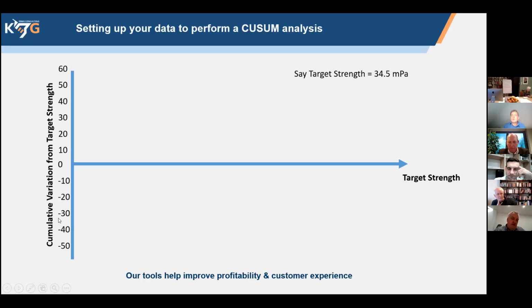On the y-axis here, we have cumulative variation from target strength, and I'll just have a very, very quick little animation to show you how the system works. So the first test result that you have, remembering the target is 34.5 MPa. The first one in the series is 37 megapascals. The plot value will be 37 megapascals minus the target strength, which is a cumulative value of 2.5. So on the graph down here, we have a line that says we're slightly above target strength.